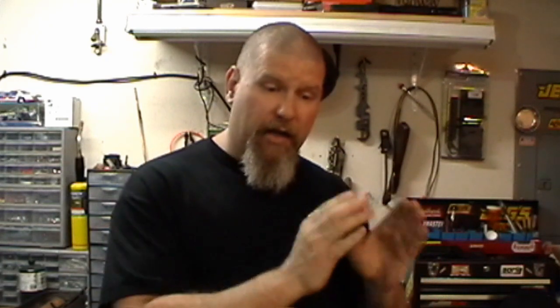And anyway, let's get to the nitride part of it. The whole rifle is nitrided, and people are like, well, that makes the metal 70 Rockwell. No, it doesn't. Not even close. All it does is give the same wear resistance of a piece of metal that was heat treated and drawn back, or tempered, to 70 Rockwell. It will not take a 20 Rockwell piece of metal, nitride it, and all of a sudden it's magically 70 Rockwell. Not going to happen, because then we wouldn't need to heat treat anything.